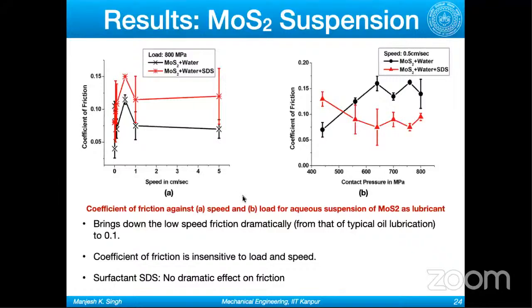And then we started with the nanoparticle in water suspensions. First is MoS2 plus water, this black one. We see lower friction. When we add the surfactant, we see higher friction. But when we plot it against contact pressure or load, the friction values are close, but the trend is a bit different, there is a switch. So what we can say is that when we add just nanoparticles to water, our friction already goes down to a very low value, like what we got with the oil lubrication. So we are getting rid of oil and getting the same coefficient of friction.